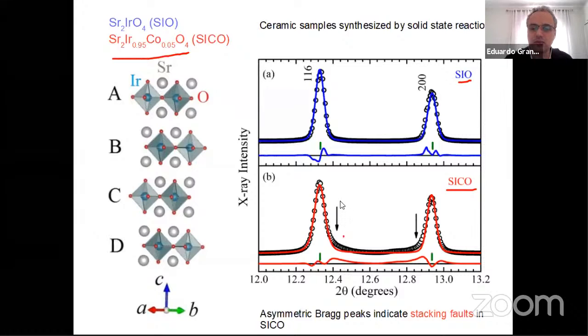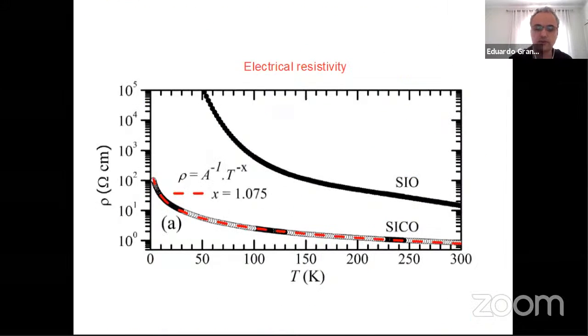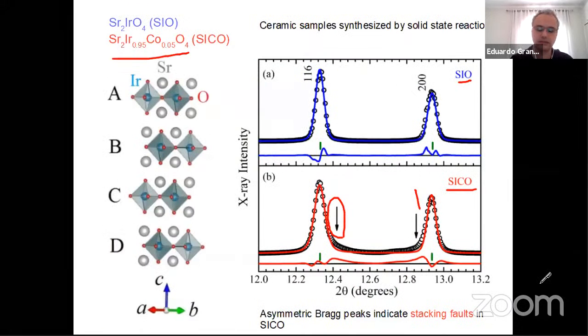We actually note some asymmetry in the Bragg peaks. You see here in the arrows that the Bragg peaks are asymmetrical for the doped sample and symmetrical for the pure sample, and that indicates the presence of stacking faults in the crystal lattice. I won't get into too much detail, but asymmetric Bragg peaks are a signature of stacking faults. It means the following: this ABCD stacking, which is pretty much perfect for the pure compound, is not so perfect when you have some 5% cobalt doping. We don't have such a perfect stacking of ABCD, ABCD, ABCD. You may have stacking faults, which are generated by the disorder that the cobalt substitution induces in the structure.